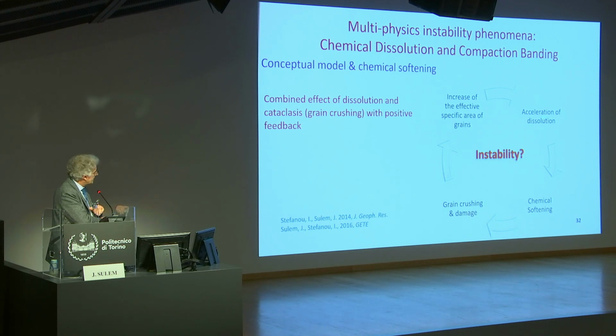So the acceleration of the dissolution will produce some chemical softening, because we know that if we have dissolution, the strength of the material will be reduced. So with a strength which is reduced, we will facilitate damage or grain crushing. So in due course of this phenomenon, we will increase the specific area of the grains, and you see that we have here this loop with positive feedback for which one